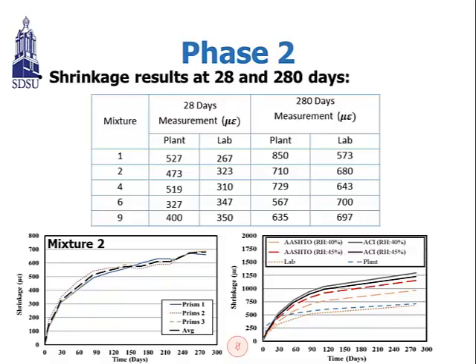And also we show the shrinkage strain using the graph showing mixture 2. As the time increased, the shrinkage of course increased. And also we compare the lab and the plant shrinkage result with the AASHTO equation and the ACI. You can see the similar trend between the AASHTO, ACI, the lab and the plant. I'm talking about the graph on the right side on this slide. But ACI is an overestimate, and the lab and plant is an underestimate of the AASHTO ACI.